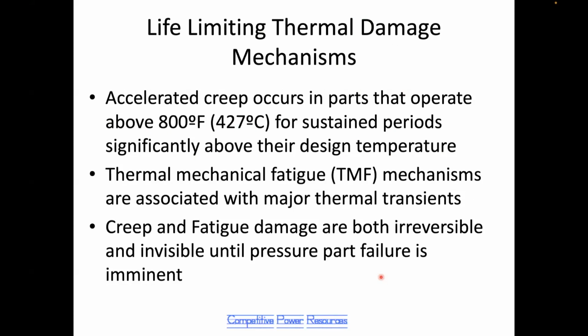So the mechanisms that occur: accelerated creep occurs in parts that operate above 427C for sustained periods and significantly above their design temperature. As I said, creep is not a significant problem today causing failures. It occasionally occurs, but not very often. Thermal mechanical fatigue is the most common failure mechanism. And as I said, it's associated with major transients that occur mostly in startup and shutdown.